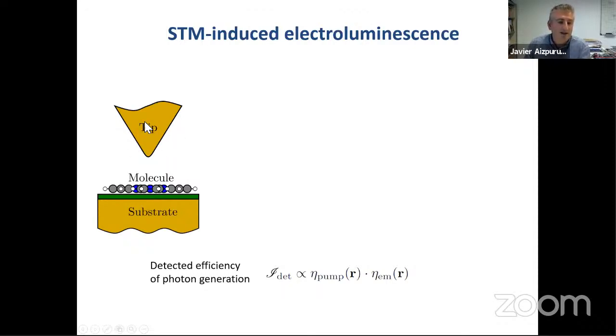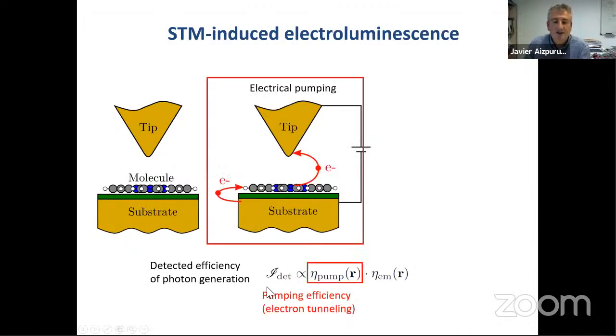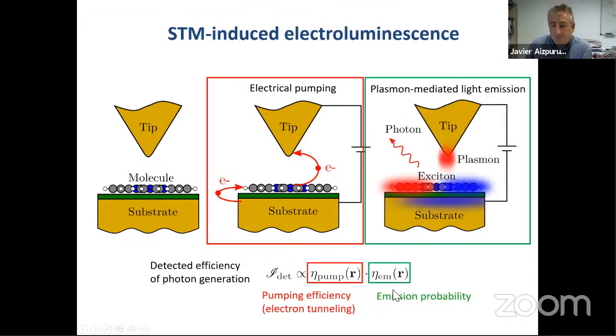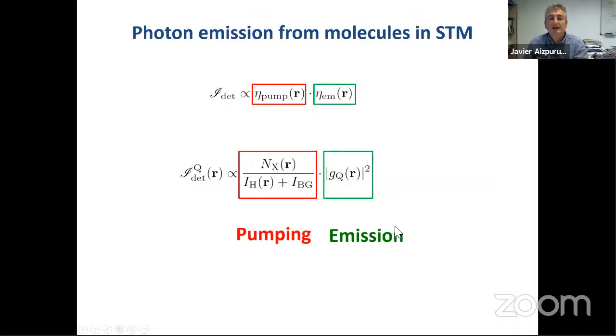This is the plasmonic tip on a substrate cavity, the molecule here, and the emission is going to be governed by the product of the pumping efficiency and the emission probability, right? So we need to inject electrons, produce the exciton, and once the exciton is produced, this exciton will emit in the middle of this plasmon cavity according to the coupling, right? So we need to address both this pumping efficiency and the emission probability. Let's do it. Let's start with emission. The emission is going to be proportional to this coupling strength squared, Fermi's golden rule. I mean, this is the emission.